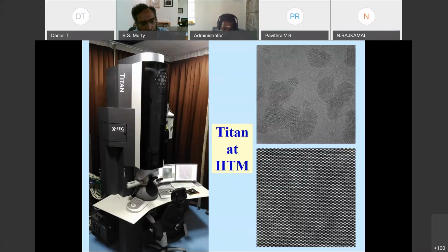For example, this microscope that you see at IIT Madras, it's called Titan, cost us about 17 crores. And you can actually see atom by atom in two dimensions. What you see on the right side bottom is silicon, the interesting dumbbell structure of silicon atoms, where each white dot that you see is an atom. And we can get a resolution with this microscope of the order of around 0.6 to 0.7 angstroms. So less than an angstrom resolution is possible with this kind of high-end microscope.